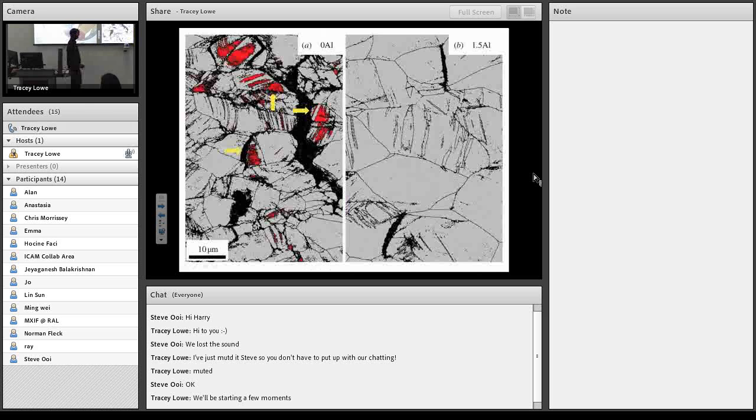Now, in the case of the low aluminium alloy, we also pick up a phase transformation. This is epsilon martensite, hexagonal close-packed martensite. So with sufficient deformation, you actually get epsilon martensite forming. It doesn't in the case where we have a large stacking fault energy. So what we did was we examined these by doing focused ion beam machining out, and putting it into the TEM to see what those facets actually are.